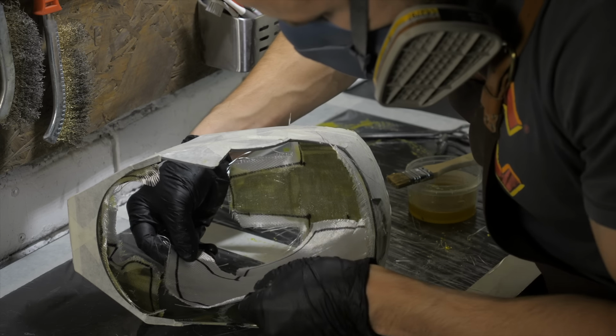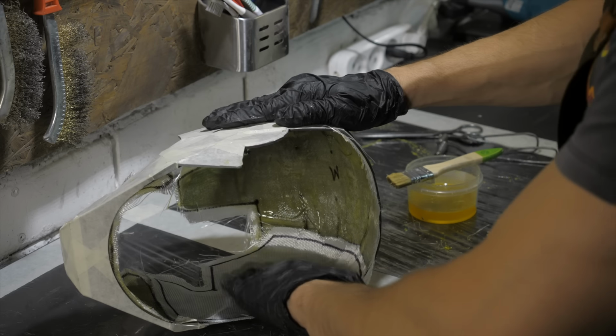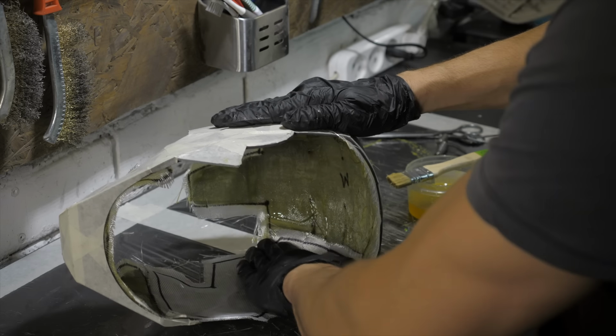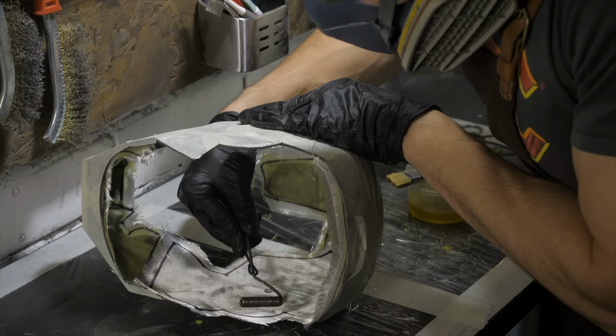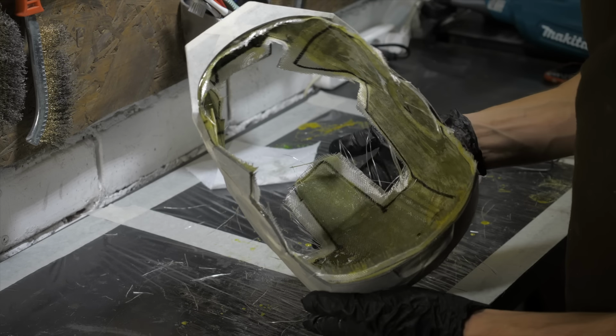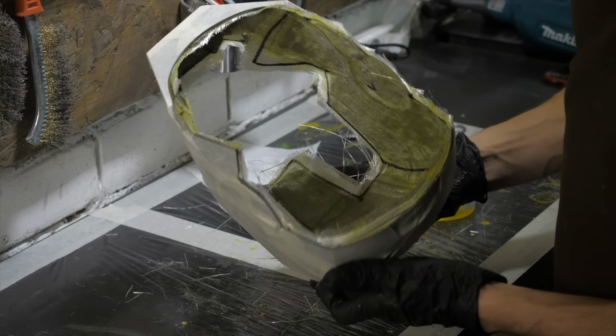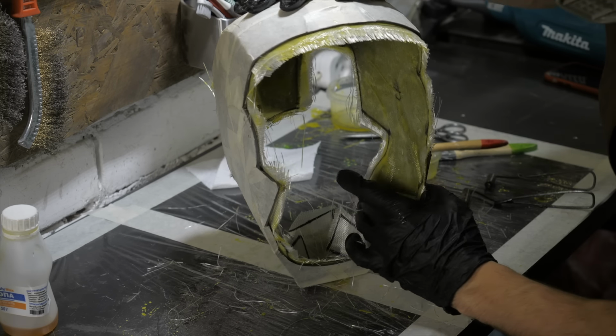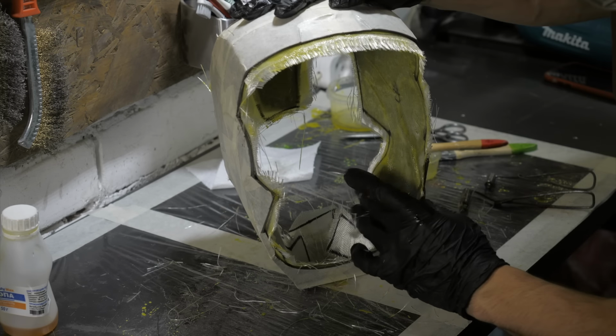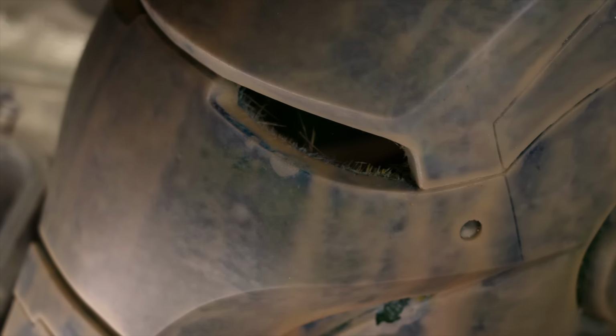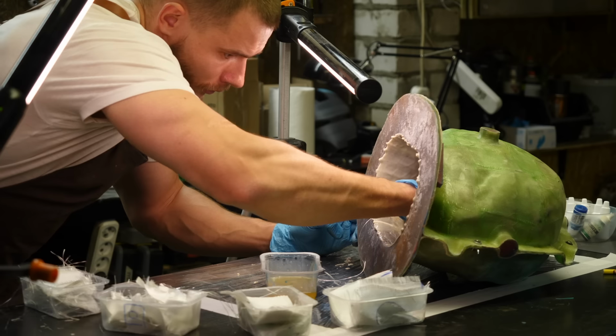Note that when laminating 3D printed parts, you don't need to obsess as much about packing undercuts, because even 2 or 3 layers of plastic have decent strength and small delaminations between plastic and composite aren't so critical. In our case, however, the thickness of the outer layer formed by the casting plastic is usually less than 1 mm. If the composite doesn't adhere to it tightly, an air bubble will form between the plastic and the composite, and as a result, the plastic in that spot could be easily pressed in even with a finger.